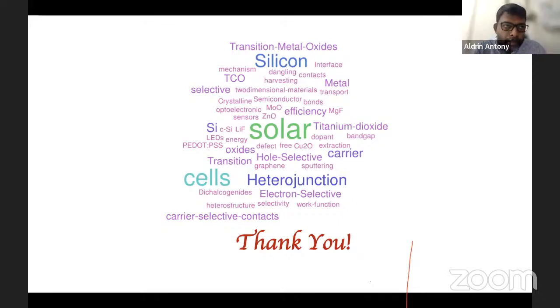For example, the electron transporting or hole transporting layers which are being used are transition metal oxides, which in principle are almost like dielectric materials. And their transparency is really high, nearly 95% compared to doped layers. When it is a doped layer, obviously there will be a lot of absorption by the free carriers. So that is the beauty of using transition metal oxides: there is no free carrier absorption with them. And it's a very thin layer, so there are no losses of absorption by these layers.